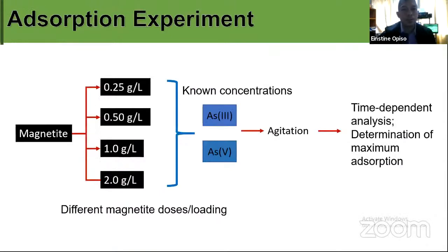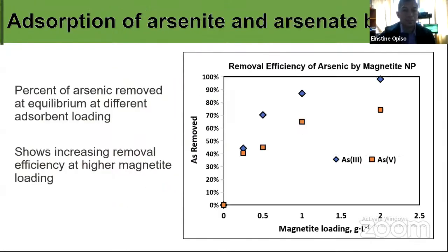So for our preliminary adsorption experiments, we have so far investigated the effect of different magnetite loading, which varies from 0.25 to 2.0 grams per liter, with known concentrations of arsenite and arsenate. These were reacted for several minutes to hours, for time-dependent analysis and determination of maximum adsorption.